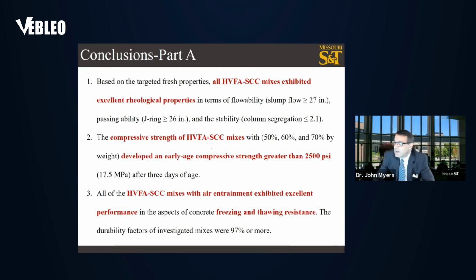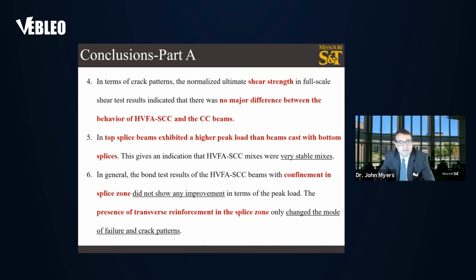Conclusions. All high volume fly ash SCC mixes exhibited excellent rheological properties. The compressive strength of the high volume fly ash SCC mixes developed an early age compressive strength greater than our target value of 2,500. All the mixes with air entrainment exhibited excellent performance in terms of freeze-thaw resistance.